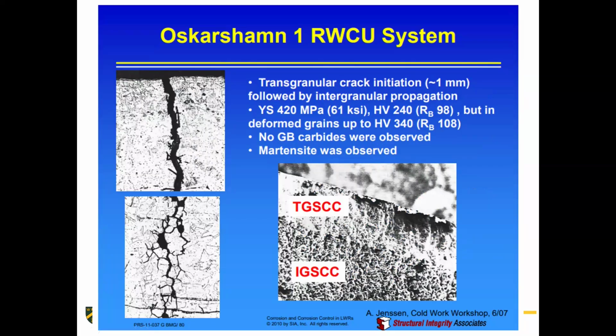Looking here, the transgranular crack actually initiated, which is how this ended up happening. You bent this whole pipe, and so what does martensite do? It's not sensitized, but it can end up kicking off transgranular cracking. Remember that's a slide I showed you before. But once you've kicked off that level of a crack, you're bound to have intergranular cracking. So you started with transgranular because of the martensite, and then that went into a series of intergranular cracks that formed through the material. You can see that network almost like an ant's nest.